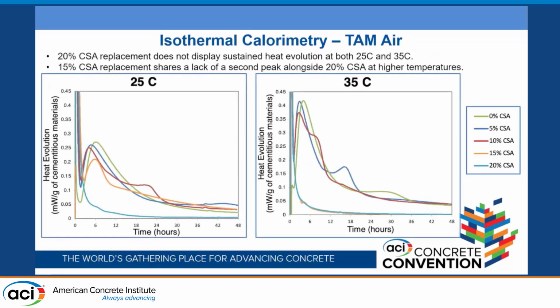So here, this is just the non-cumulative heat evolution of the samples, and you can see quite clearly how the 15% CSA, or the orange line, is able to maintain somewhat of a peak, even at 25 degrees Celsius, whereas the 20% CSA has a steep drop-off. At 35 degrees Celsius, both of them have a steep drop-off, don't appear to have a second peak, and are almost identical. You can barely see the splitting of the two.